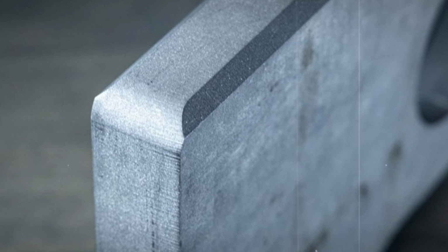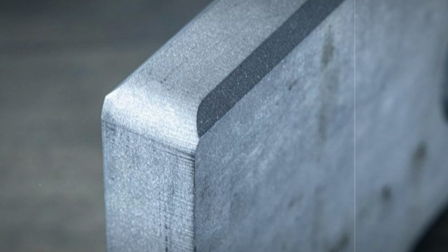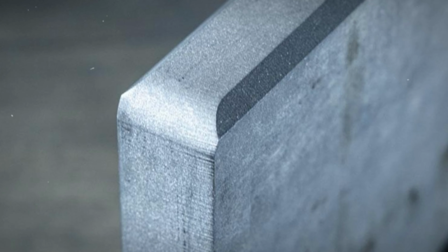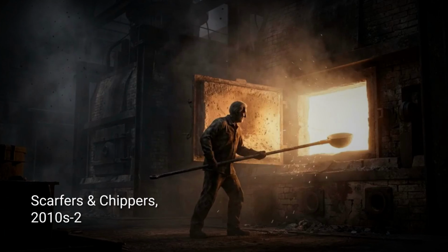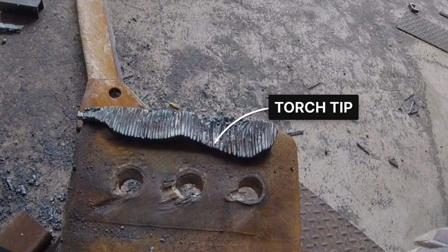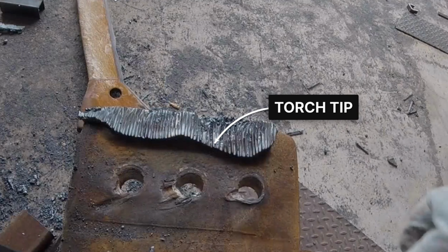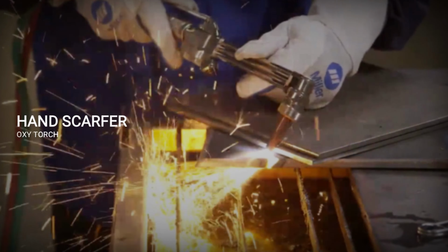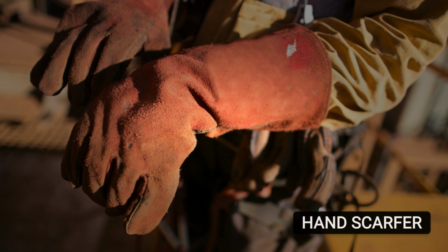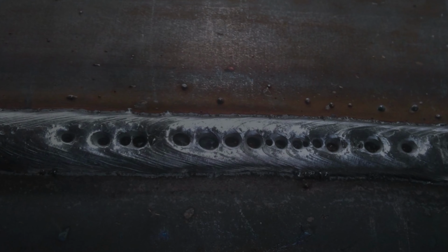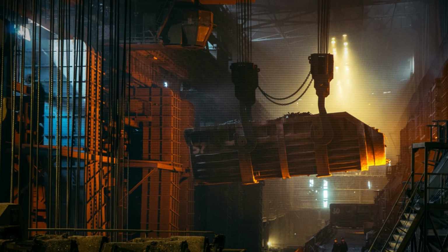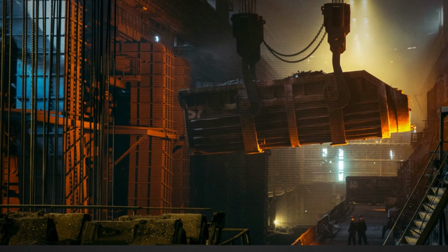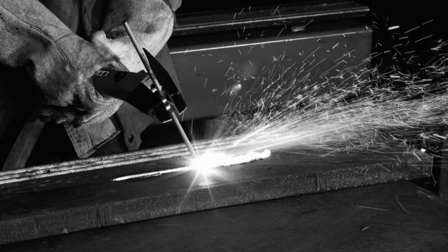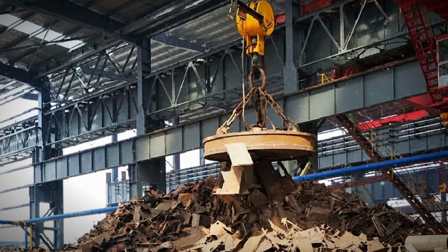Number 6. Scarfing by hand. Steel came out of the mill wearing its mistakes on its skin, cracks, seams, patches of bad surface, and the men who removed them were called scarfers and chippers. A hand scarfer walked the slab yard with an oxygen torch that roared like a jet, and he burned away defects in shallow, controlled washes, steering a puddle of burning steel with wrist movements measured in millimeters. Go too shallow and the crack survived, hiding, waiting to open up in some customer's forging press. Go too deep, and he gouged the slab, scrapping value with every pass.